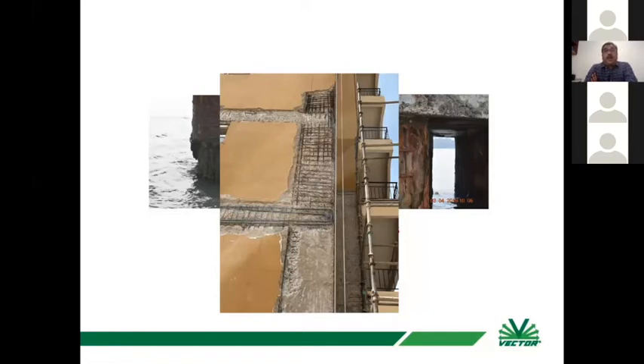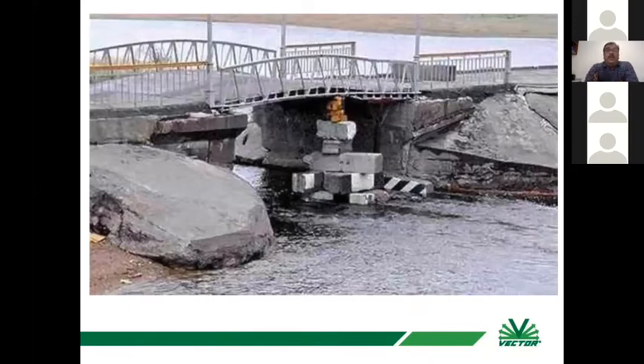But the chloride is there from the first day, which is a cancer for the concrete, and it starts corroding the rebar, and then it leads to structural failure. We don't want these failures because of corrosion. And what we do is we take care of it by a jugaad. As far as the Indian context is concerned, the parapets are painted properly, and there is a temporary support taking care of the flow of water and the angle of repose, 45 degrees, and wooden logs. Fine, it will stay, but it will not stay for long.